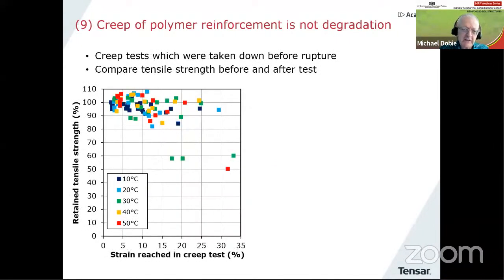How does it work then? Well, in our own creep laboratories, we have quite a few creep laboratories. For many years, every time we took down a creep test, even one after several years, we would check its tensile strength using the same procedure to measure the tensile strength before the test started. And then we compare the two. So here is a graph showing the retained tensile strength compared to the strain reached in the creep test.